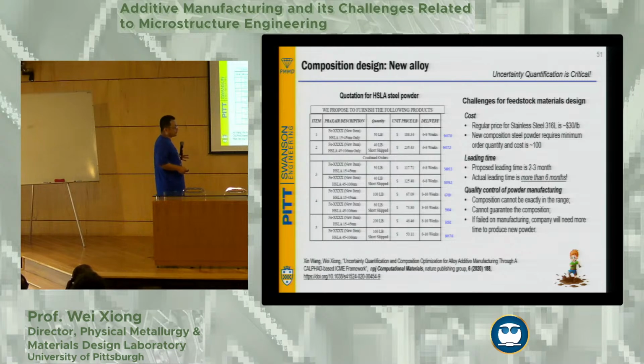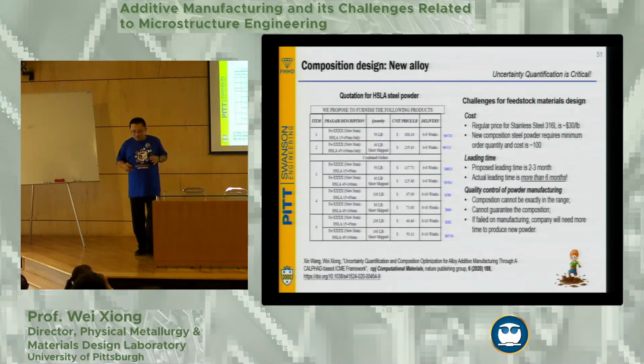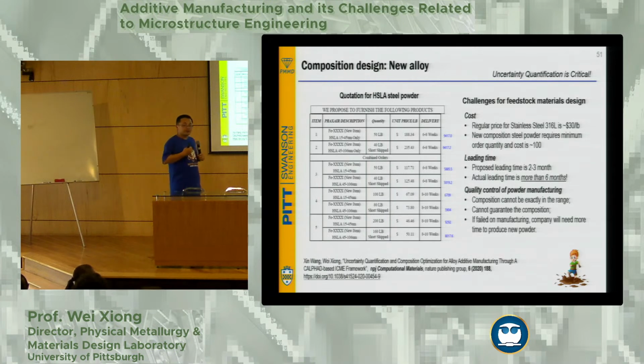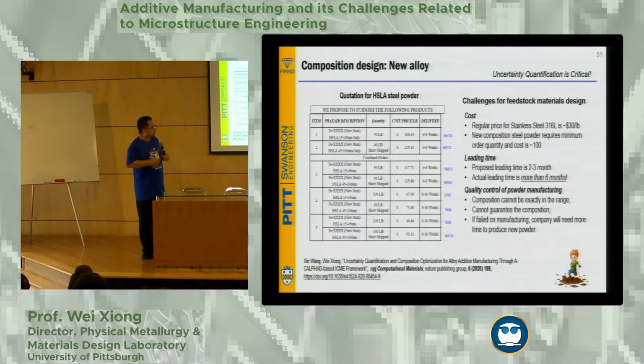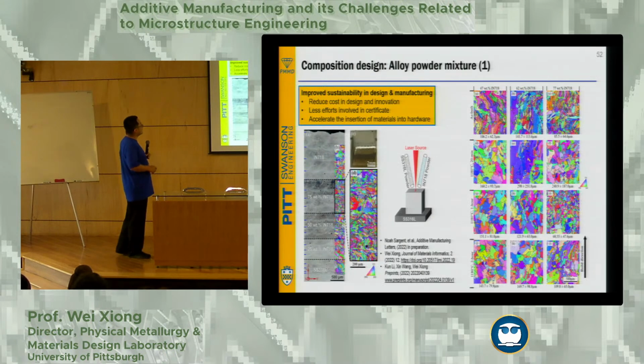Of course, still, if you get a lot of funding, you can test, right? One of our strategies is to try to design some potential alloy with a prototype, which we can do by casting, arc melting, and checking some microstructure features. For example, if you want to design an alloy for additive manufacturing with particle strengthening, you can do the test with a traditional arc melt, right? So get a sense of whether the phase stability is okay or not, right?